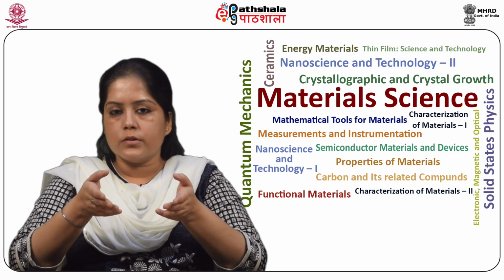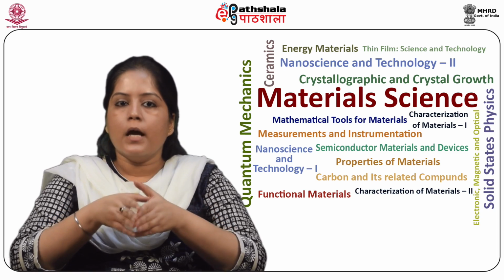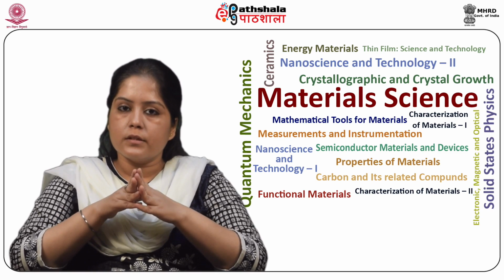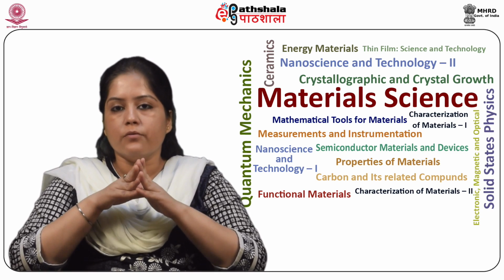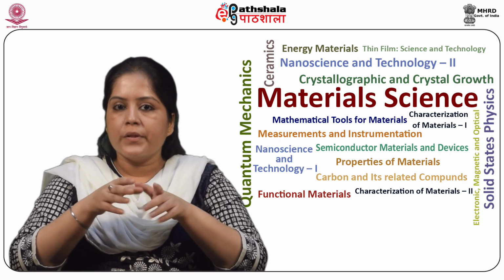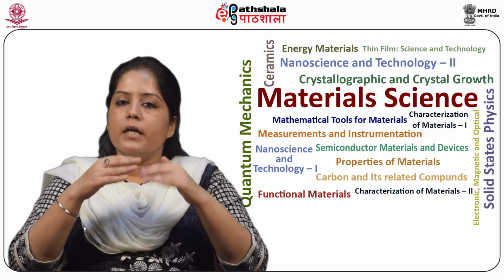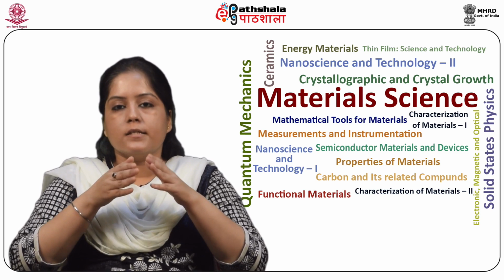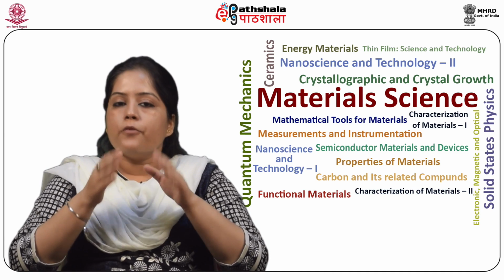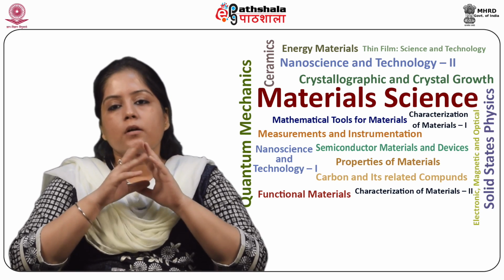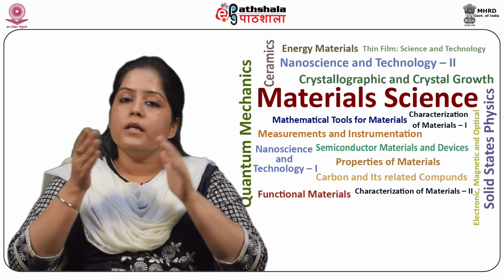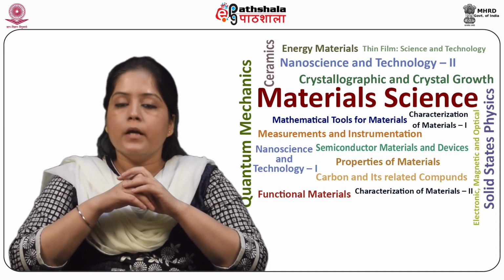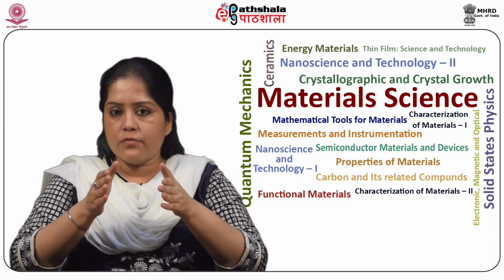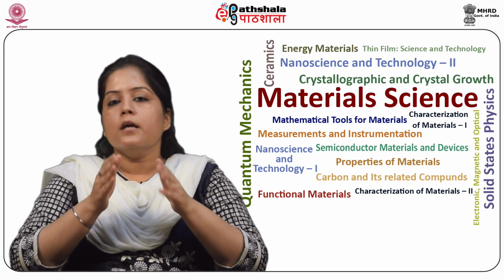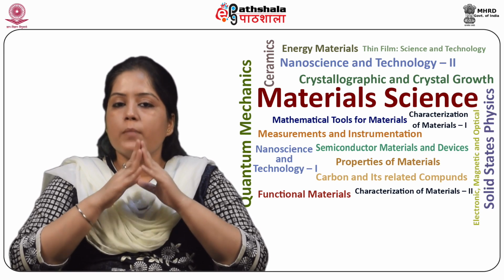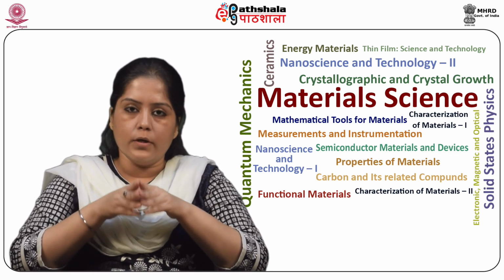Experiments were carried out to study this effect, and it was finally concluded that the electrostrictive coefficient, that is Q, increased with the order level of the B-site cations from disordered to partially ordered and then to the ordered structures. In order to explain this phenomenon, K. Uchino proposed a schematic crystallographic model.